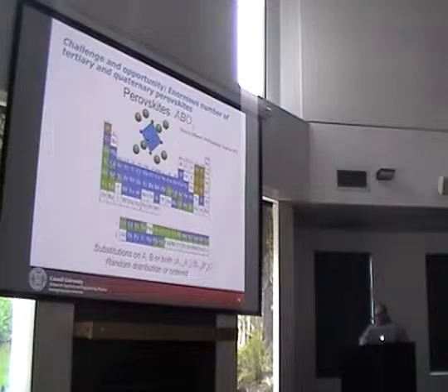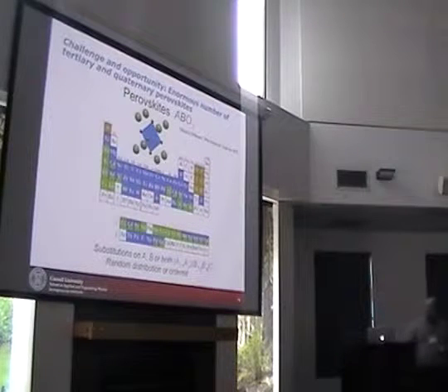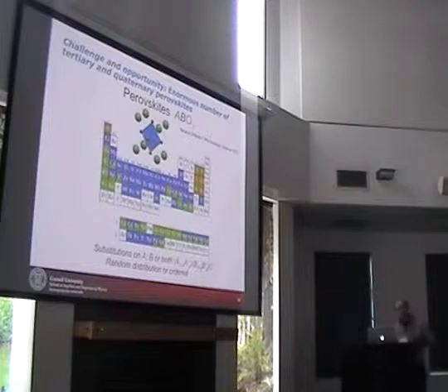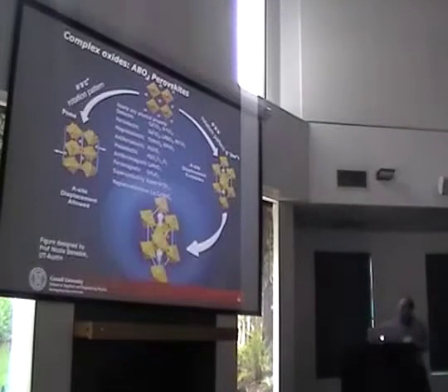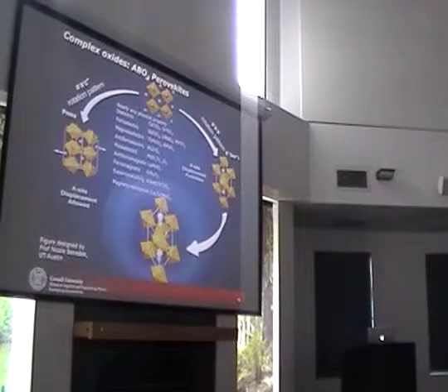If you think about the various size differences of these primarily ionic cations and anions, you can question how this one structure accommodates all this chemical diversity. It's that this idea that we have this cubic perovskite is a bit naive. Very few perovskites are actually forming a cubic structure. Most of them, in order to accommodate all of these different cations, distort. The octahedra distort in various patterns.